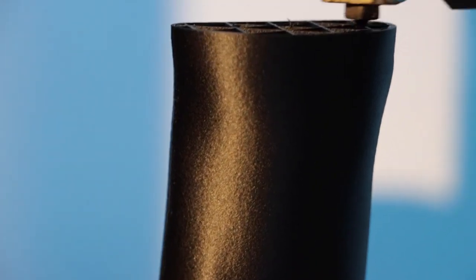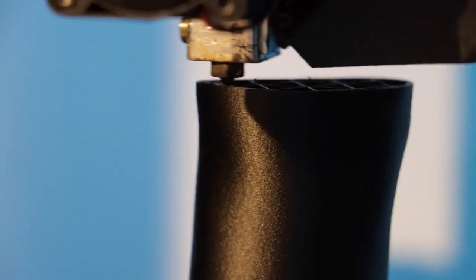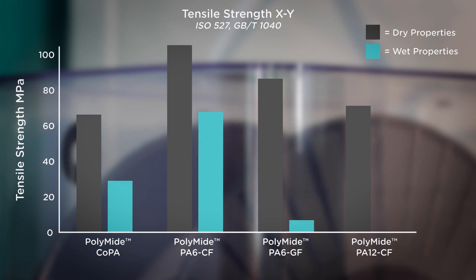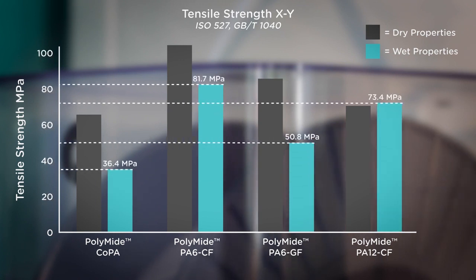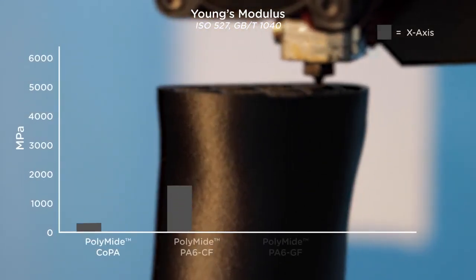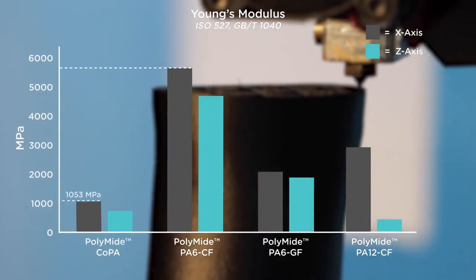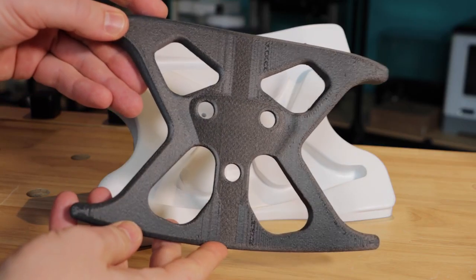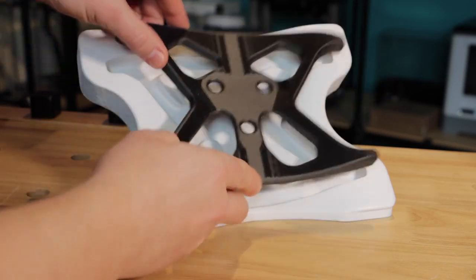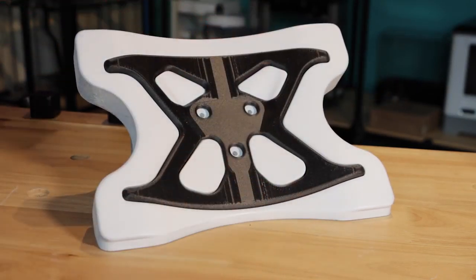As PolyMide PA12-CF also has a lower percentage of carbon fiber reinforcement, you will notice a smoother and higher quality surface finish on your printed parts. If you require outright strength, then the 20% carbon fiber reinforced PA6-CF is one of, if not the, strongest and most durable 3D printing filaments available on the extrusion-based market. If you need a nylon with exceptional printing quality, high strength and a spool that won't be affected by moisture over long periods of time, then PolyMide PA12-CF is clearly the best filament for your application.